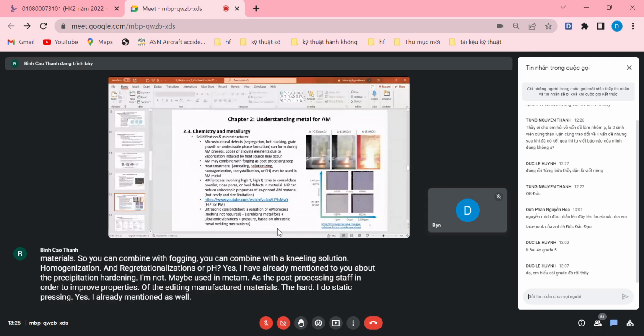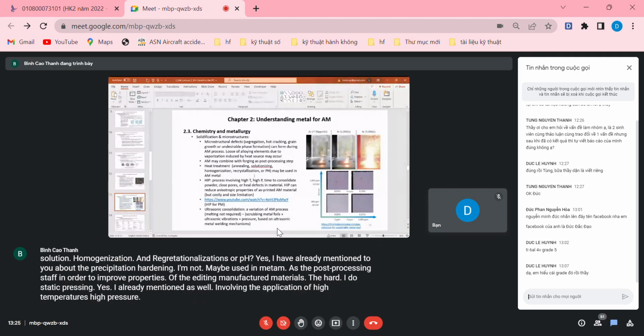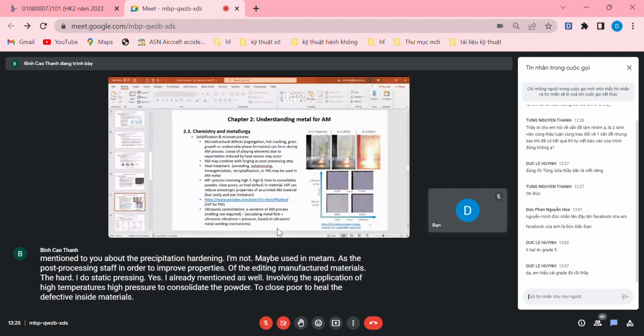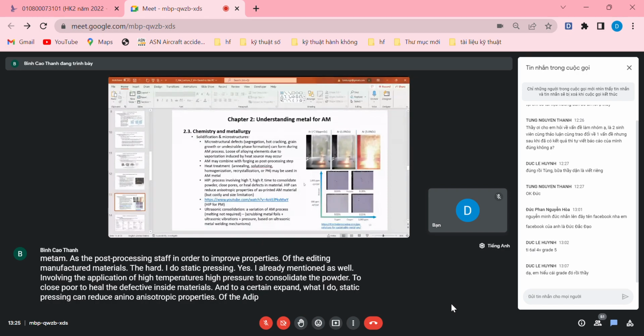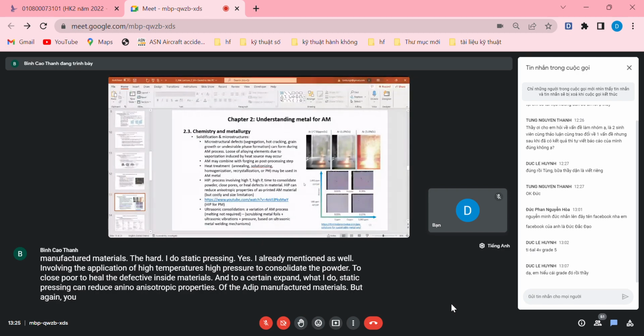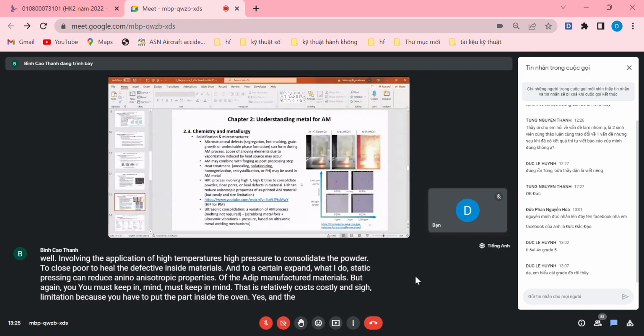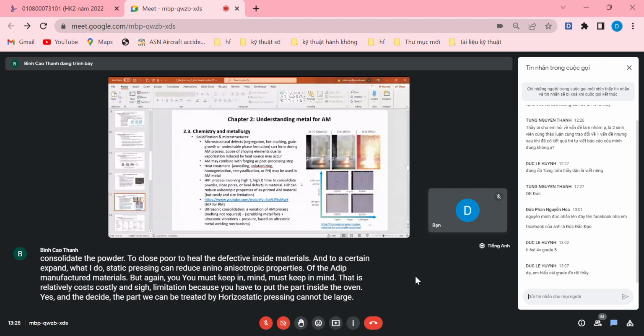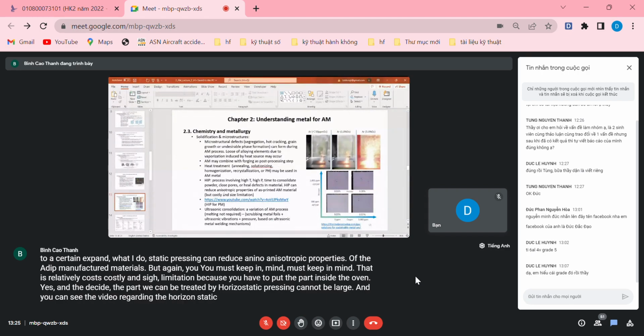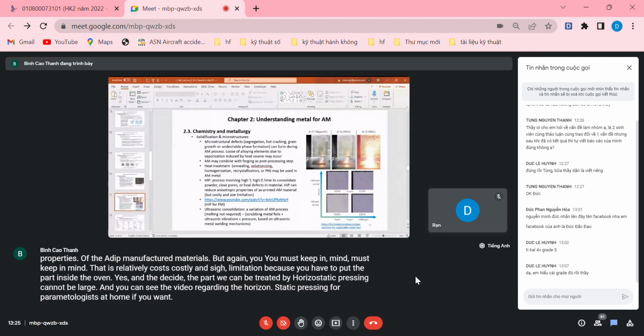The hot isostatic pressing, which I already mentioned as well, involves the application of high temperature and high pressure to consolidate the powder, to close pores, to heal the defects inside the materials. And to a certain extent, hot isostatic pressing can reduce anisotropic properties of the additive manufactured materials. But again, you must keep in mind that it is relatively costly and has size limitations, because you have to put the part inside the oven, and the size of the part which can be treated by hot isostatic pressing cannot be large. And you can see the video regarding hot isostatic pressing for powder metallurgy at home if you want.